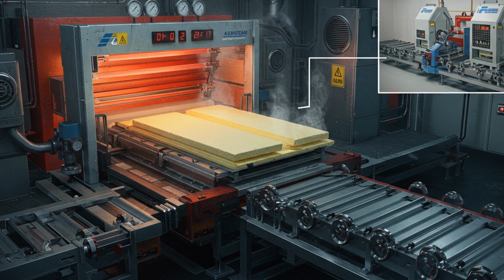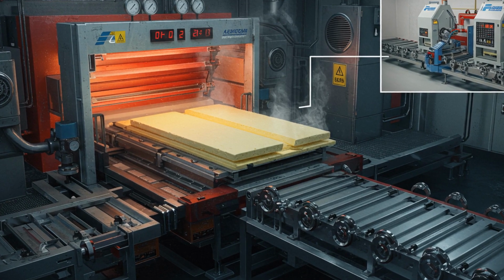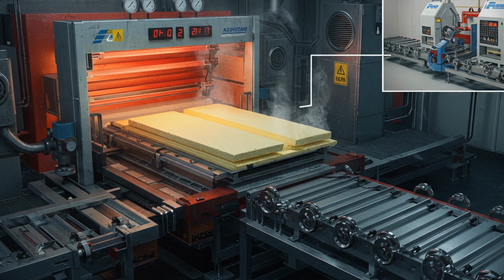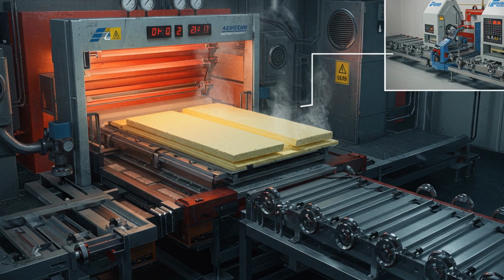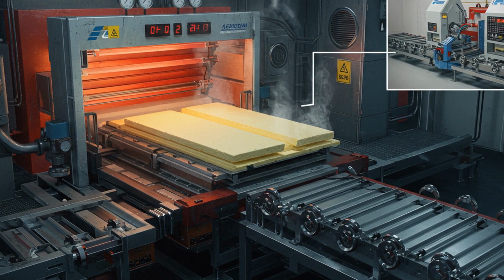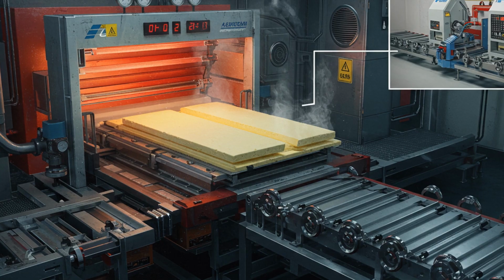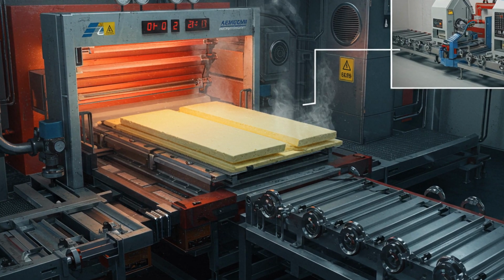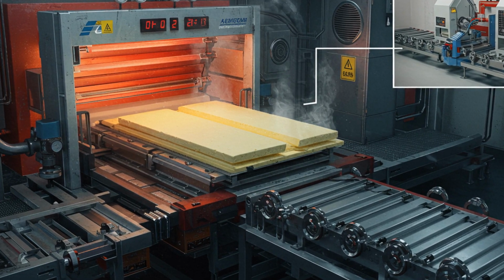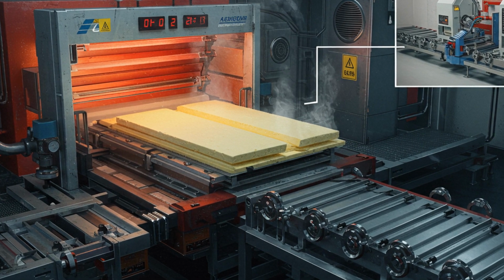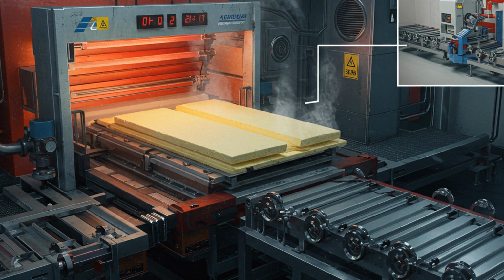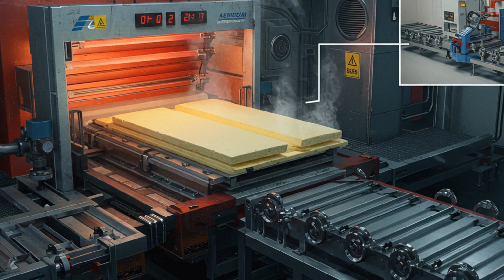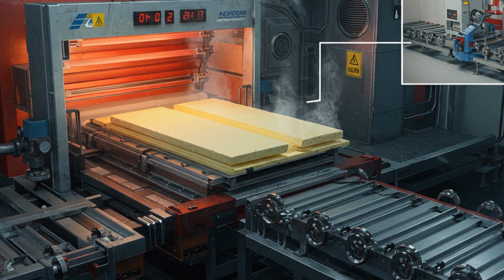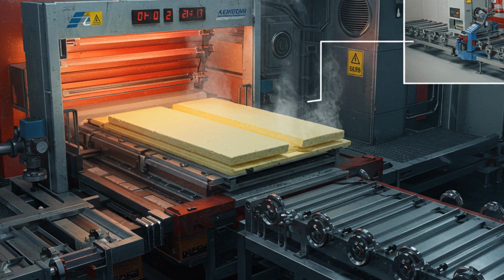Temperature control is critical. Many plants hold slabs at about 110 to 140 degrees Fahrenheit to accelerate cure without degrading surfactants. During cure, crosslinks form and chains lock into the viscoelastic network that gives memory foam its slow recovery. Manufacturers often perform thermal aging or vacuum flashing to reduce volatile organic compounds, off-gassing that consumers can smell. Sealing and post-cure can lower VOCs by 50% or more.